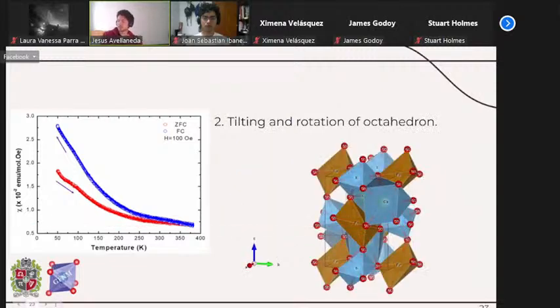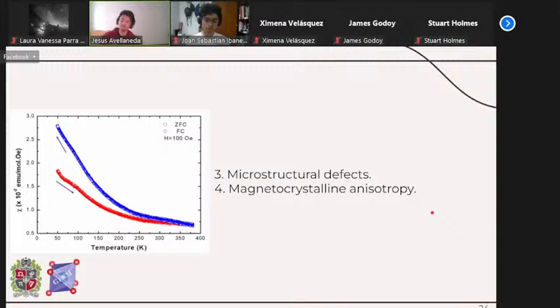For the second part, tilting and rotations of octahedra, this basically is a no doubt because, as my friend said, we can corroborate with the Rietveld analysis carried out that the structure obtained in Vesta shows these inclinations and rotations. So we can attribute this behavior to said phenomena. For the microstructural defects, these cases can include vacancies, interstitial or substitutional defects, precipitates, and impurities that should be expected due to the method that we use, the solid-state reaction. So it is a thing to take into consideration.